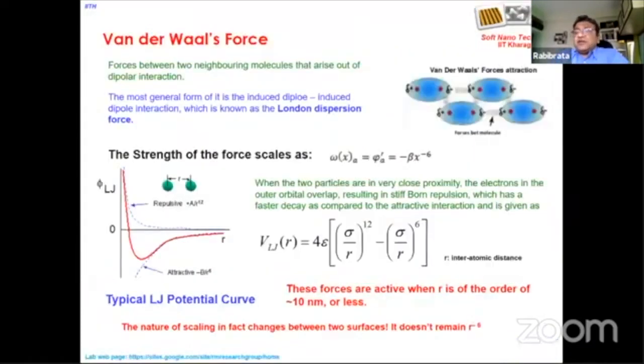But there is another aspect of nanoscience, or the nanoscale, which is not that well appreciated, and that is that this length scale is entirely dominated by van der Waals interaction, or intermolecular interactions. Probably many of you are aware of the van der Waals interaction, the most common being the induced dipole type interaction. The strength of this interaction scales as 1 by x to the power 6. And please remember that the gravitational potential energy scales as mgh. So it's h to the power 1, and here it is h to the power minus 6. It's very simple mathematics that if you keep reducing h at very low length scale, mgh tends to 0, while 1 by h to the power 6 picks up.